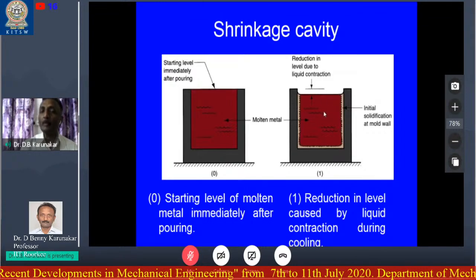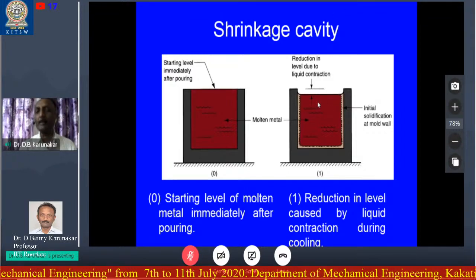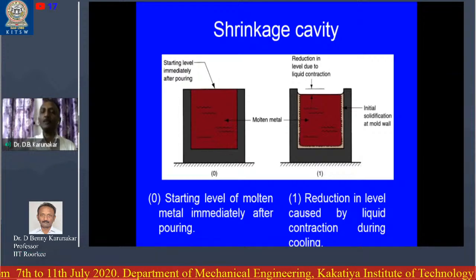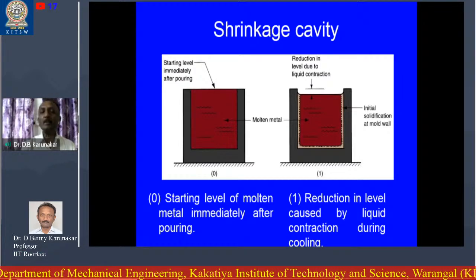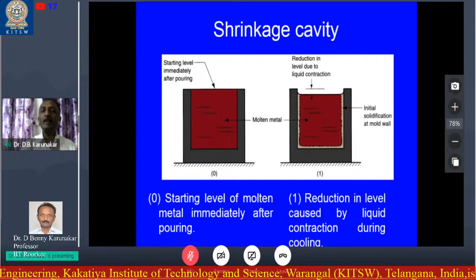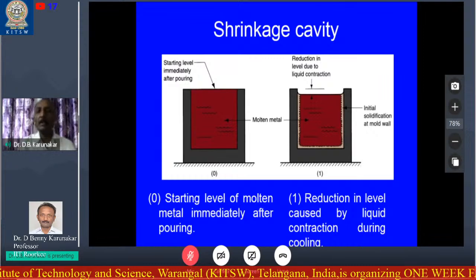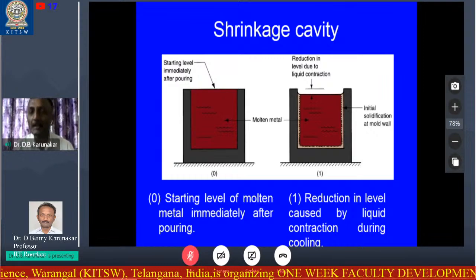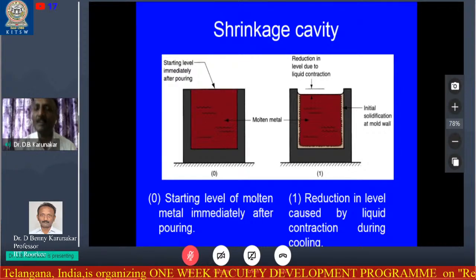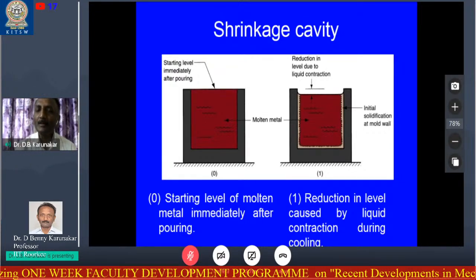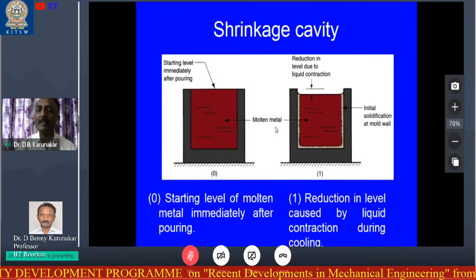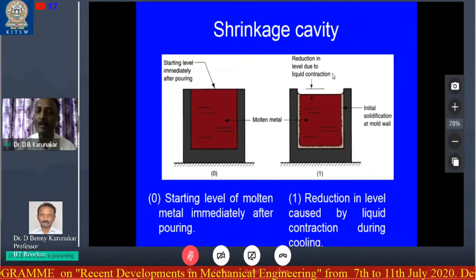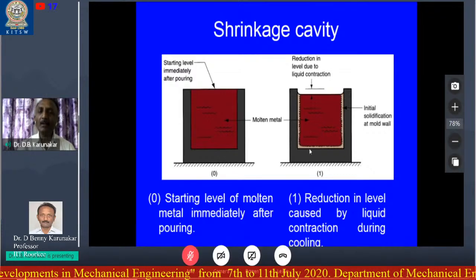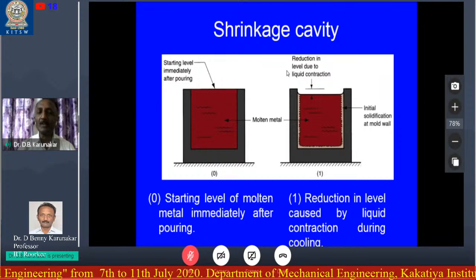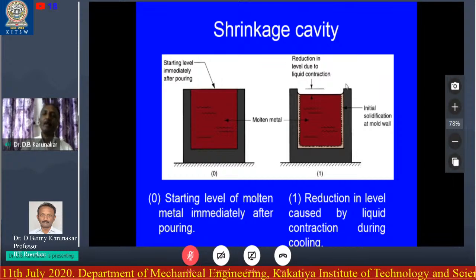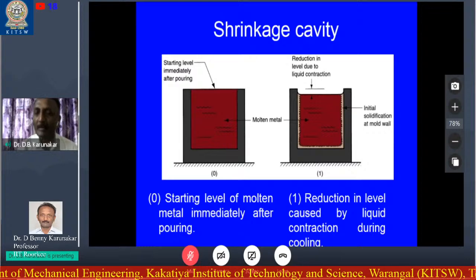Now, when you pour the molten metal at the pouring temperature, what happens? The temperature slowly comes down, from the pouring temperature to the melting temperature. For example, if we pour the molten aluminum at 750 degrees centigrade, then from 750 to 660, it will be in the liquid state only during that stage. Now, during that stage, there is liquid cooling, so there is a contraction. You see? So, this is the liquid contraction. Remember, this liquid contraction will be there whenever we are making a casting.